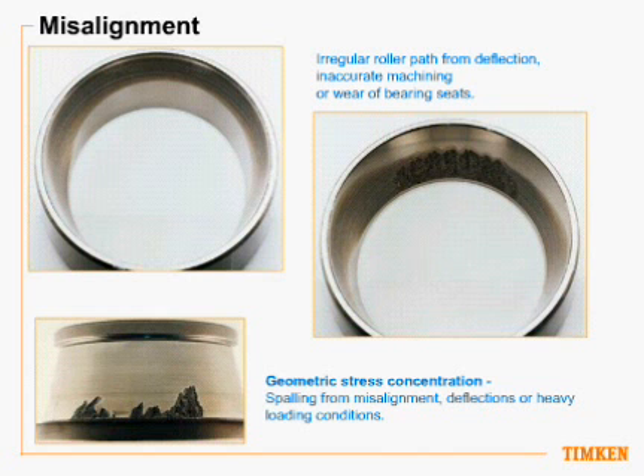Okay. Another would be excessive end play, and what I mean is if you have this assembly so loose that the hub will actually drop or tilt. If you were to play with these, when you put the two bearings in there and adjust them up, you're pulling it in and out. Basically the hub doesn't shake up and down; it just moves a little bit in and out. But if you were to have excessive, and I mean more than 7 thousandths or 10 thousandths, what you're going to notice is that the hub will actually start to rock, and what that is, you're misaligning the bearings. It's actually shifting, okay, and not even load distribution all the way across the rollers.